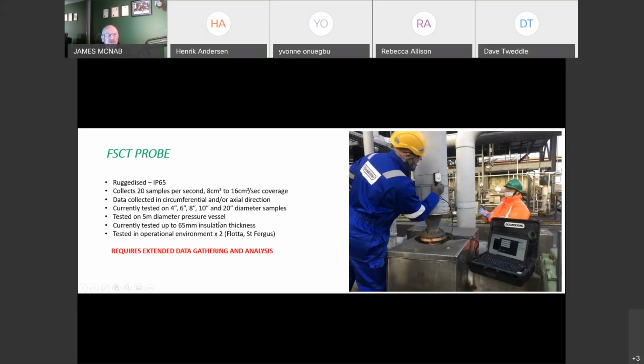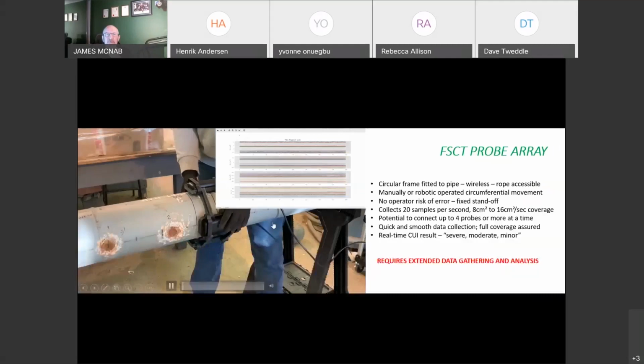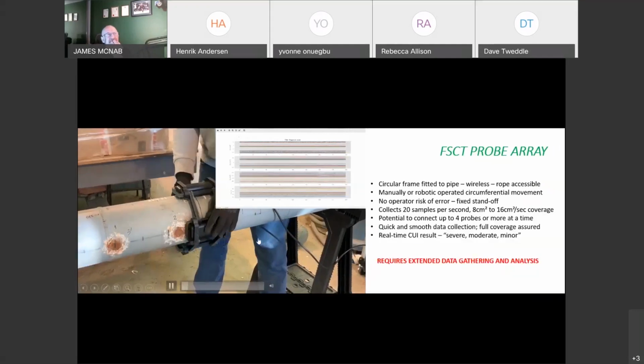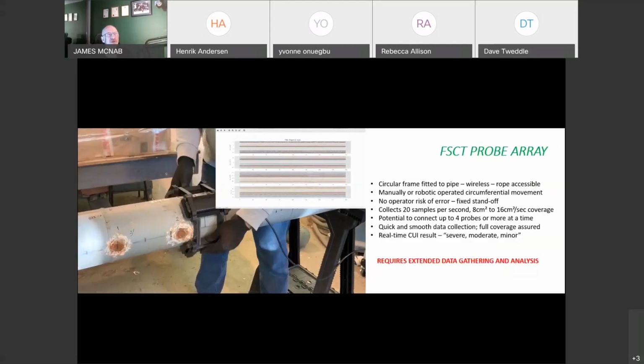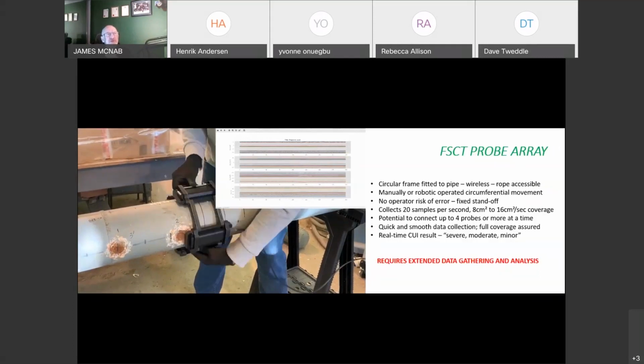It's also been tested on a 5 meter diameter pressure vessel, currently tested up to 65 millimeters insulation thickness, and thanks to Repsol, Sinopec and Shell for allowing us to get to their plant in St Fergus to try it out. But the red writing at the bottom says it requires extended data gathering and analysis, and we're still at that stage.